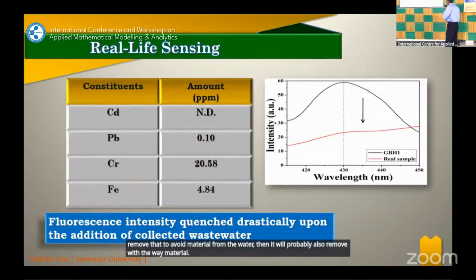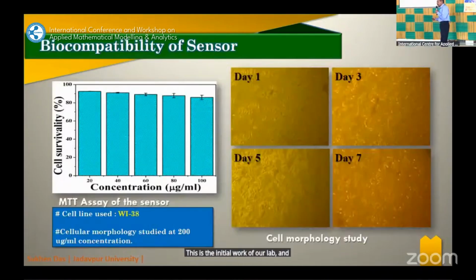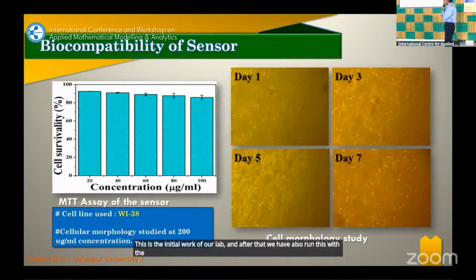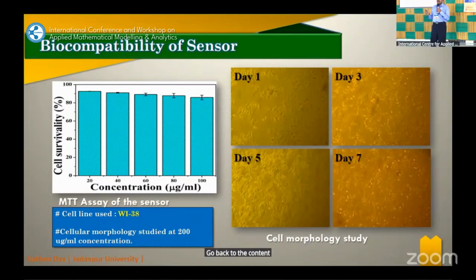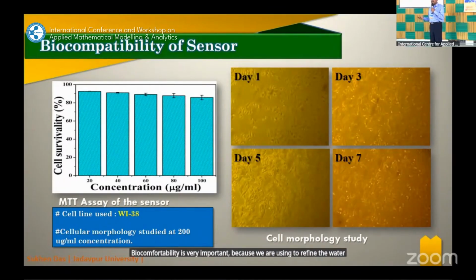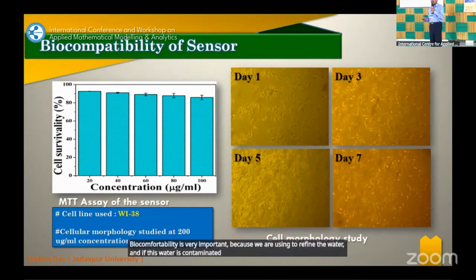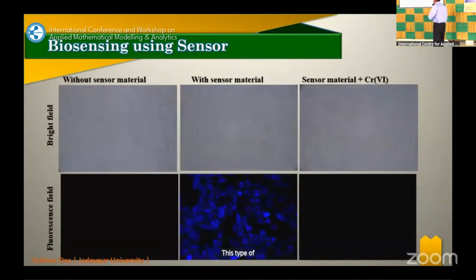This is the initial work of our lab, and after that we have also run this with the WI-38 cell line, and from there we have seen that this Boehmite material, the Gum Acacia containing Boehmite material, is not harmful for our body, because from the cell line we have observed this. So the biocompatibility test is very important, because we are using it to refine the water, and if this water is contaminated again, then it will be difficult. That is why we tested with the cell line. This type of fluorescence property we find in the presence of that Boehmite, we will get a fluorescence property like this.